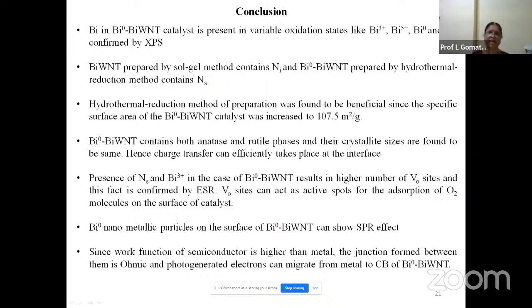The oxygen vacancies can act as active spots for adsorption of oxygen molecules, which is very much necessary to trap the conduction band electrons, and Bi0 nanometallic deposits on the surface of BiWNT show the surface plasmon resonance effect. Another important thing I had not mentioned here is that the work function of the semiconductor is higher than the work function of the metal. Therefore, the junction between the two cannot be called a Schottky junction. Instead, we can call it an ohmic junction. That means Ohm's law is followed at the junction.